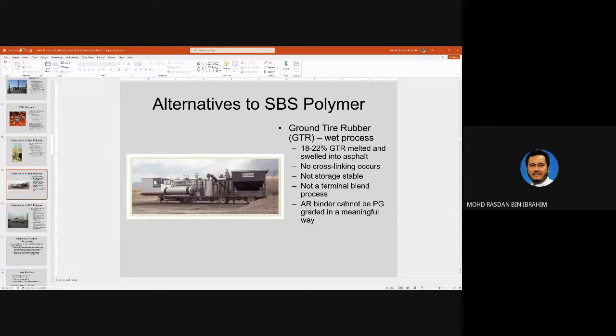Asphalt rubber cannot be PG graded in a meaningful way because the particles of the rubber normally will cause the result to go a little bit haywire if the particles are big. So the size of the particles usually is between 250 microns to 400 microns. That is 0.25 millimeter and 0.4 millimeter.